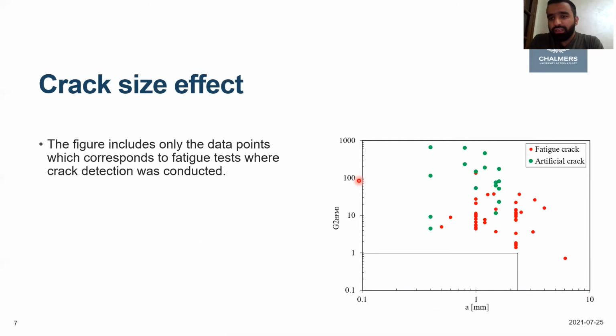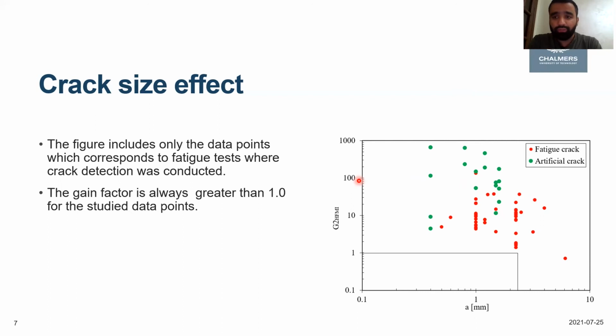What we need to find is the gain factor. If it's greater than 1, that means HFMI treatment has the potential of improving the fatigue life even when the structure contains cracks. And this is what we found, that we always got the gain factor to be greater than 1 for almost all the data pool. It is worth mentioning that only the data points which contain fatigue cracks are included here in the figure. So this is much less than 130 data points, but for all of them, the gain factor is greater than 1.